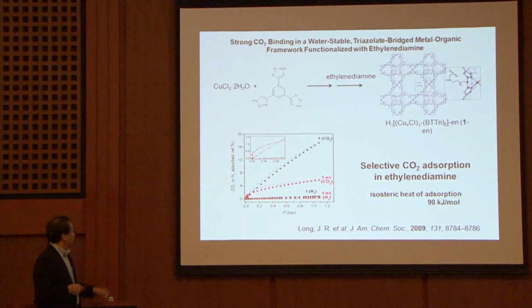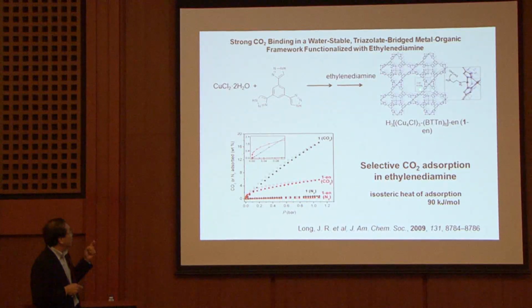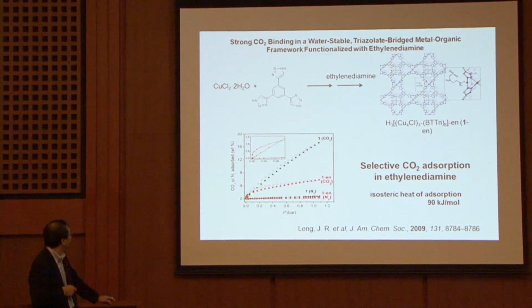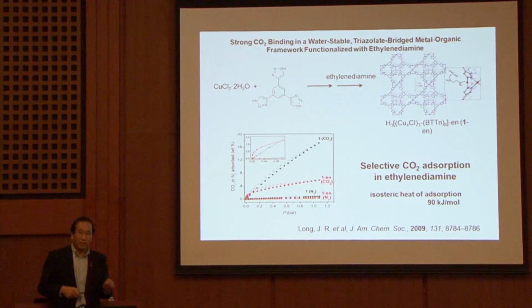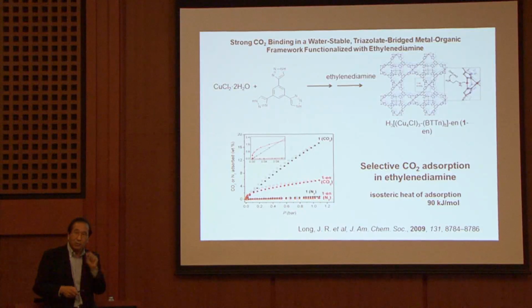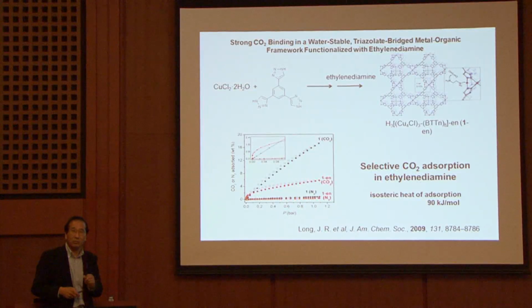One way to use this is a very authentic idea. This is the kind of framework having the stronger interaction site for CO2. So Jeff Long synthesized a very, very useful framework system with very high affinity for CO2. It's very good, but the problem is, how do they remove CO2?